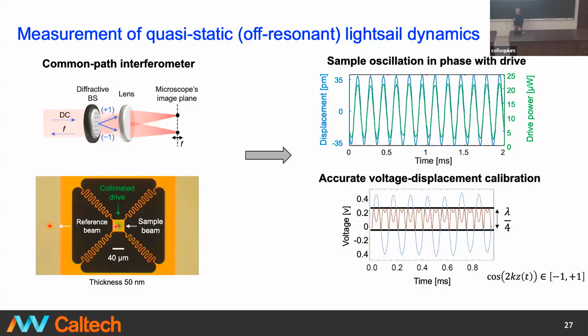What we do is we reference this to a rigid silicon frame. It's of course moving, because the ultra high vacuum system in the lab is moving. It's whatever the speed the floor is moving and so forth. But by unfolding these oscillations, we can determine the harmonic displacements of the light sail itself with something in the range of 5 to 10 picometer resolution. And the neat thing about this is that we can probe with effectively a diffraction limited beam spot with this kind of displacement resolution out of plane.